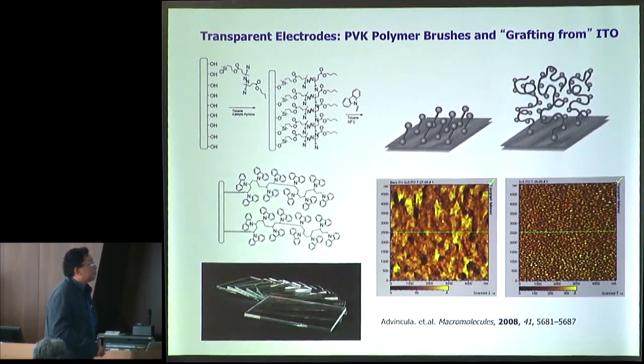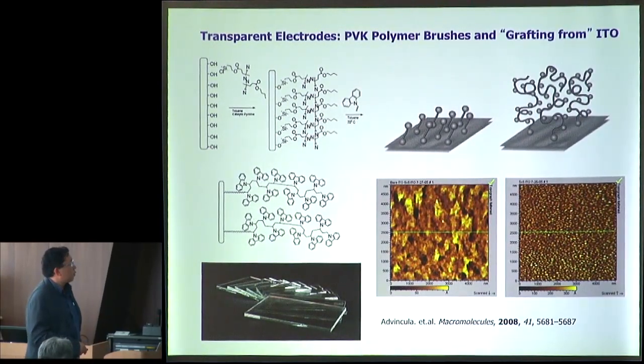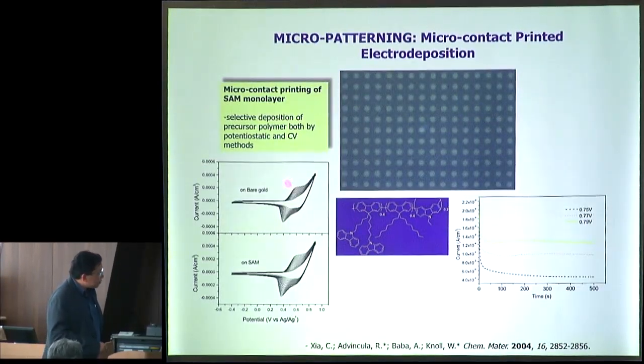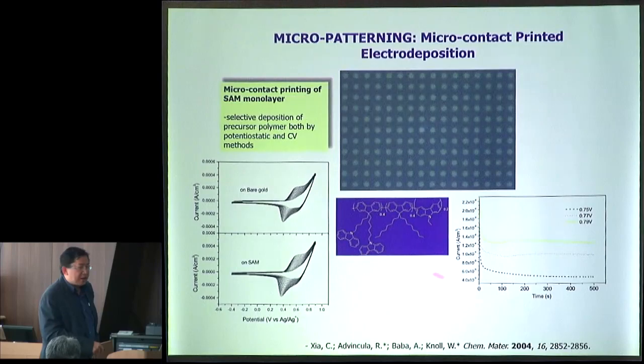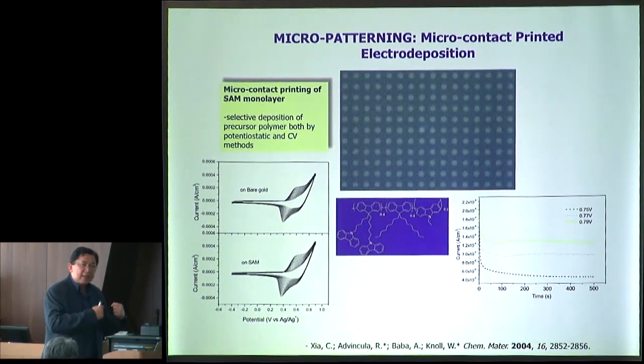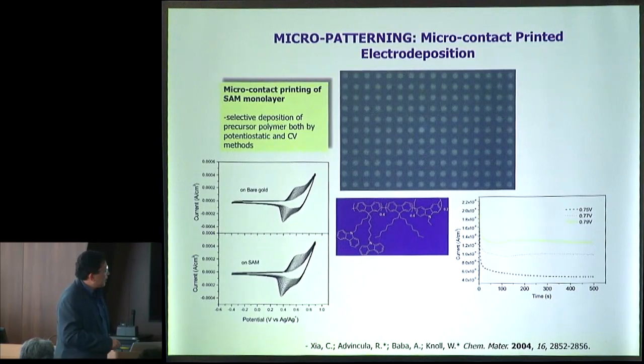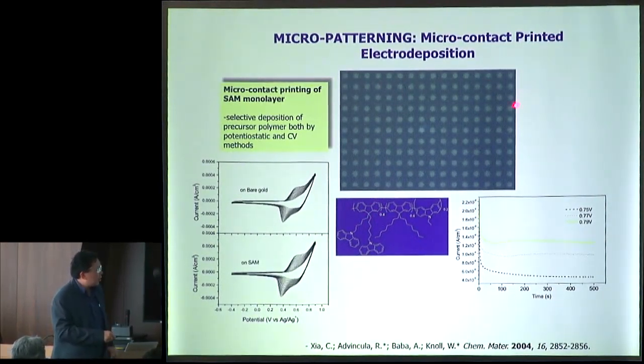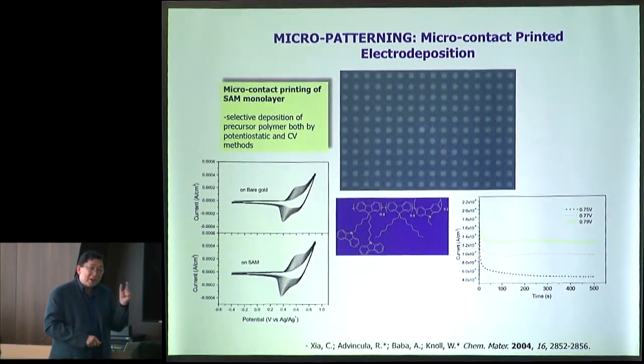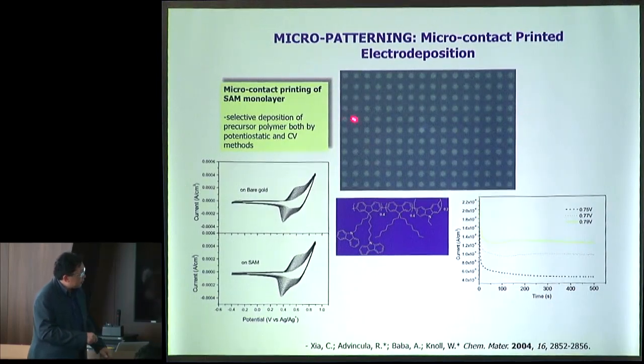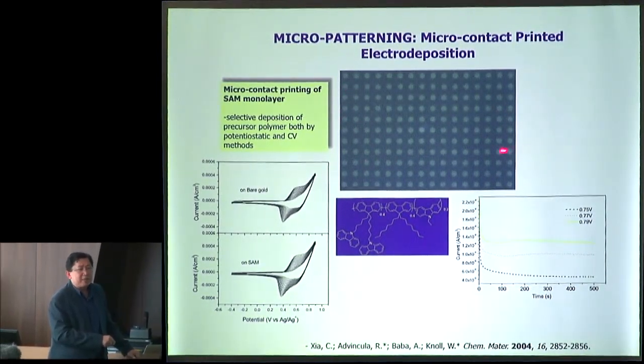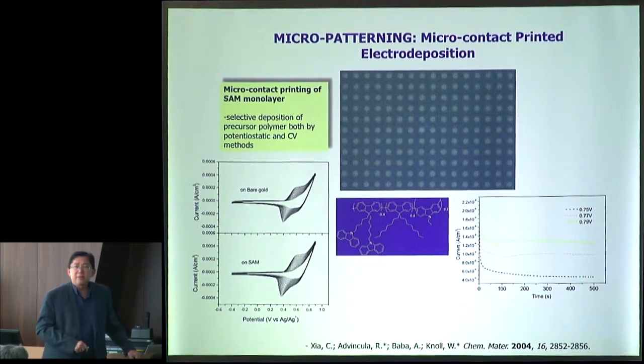Let me skip that part showing the performance, but rather focus on a specific aspect of patterning. This was a polyfluorene that we synthesized, having carbazole units that like to cross-link because of the carbazole group. And then what we did is we patterned it on a substrate with 25 micron dot structure. So these are 25 micron electrodes. And notice here we get very nice contrast of the blue emitting material, because electrochemically we can site deposit on this dot structure in the presence of this carbazole.